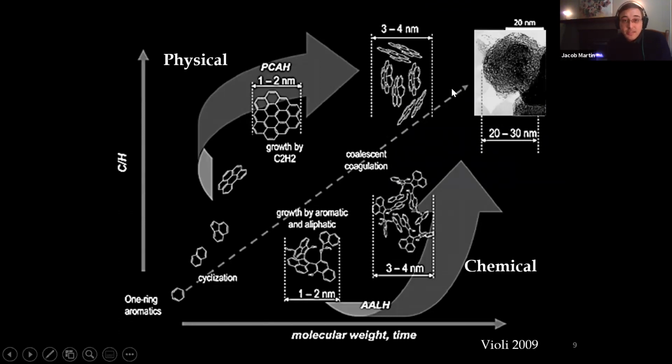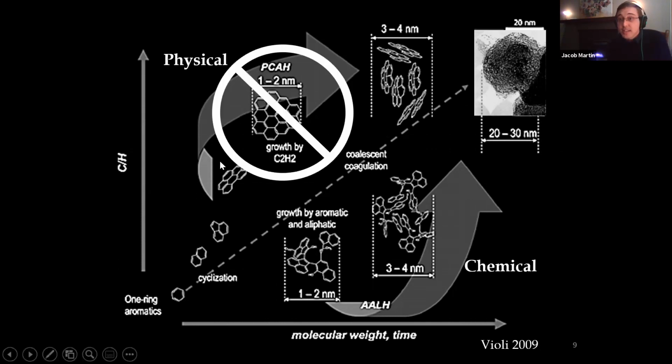The first is a physical mechanism whereby the molecules grow to a size which is large enough that their physical interactions mean that they condense in the flame, so they form droplets. Now, you can compute the energy between these molecules, and you can look at the size of molecules in the flames, and you find that they are far too small to justify having a droplet at flame temperatures. So that's not happening. The second option is a chemical mechanism whereby you get radicals that can then polymerize and form kind of like a polymer. You can also work out from first principles the rate at which these cross-links could occur. And you find for this type of cross-linking reaction that's been proposed, it is also far too slow to explain the formation of soot. So that can't happen.